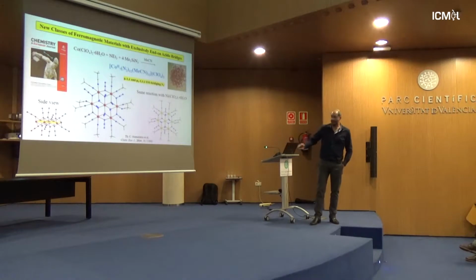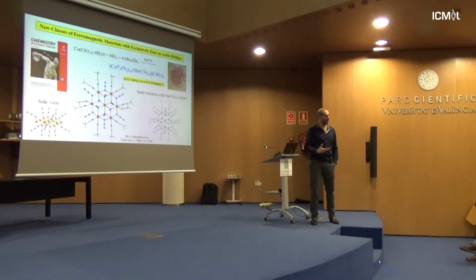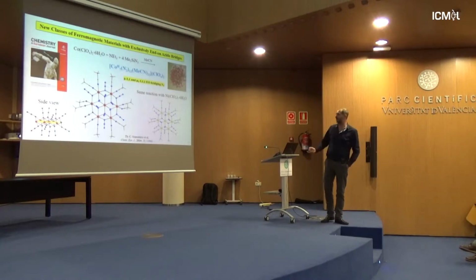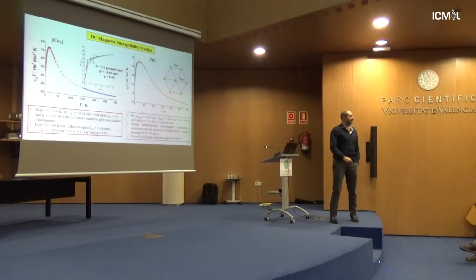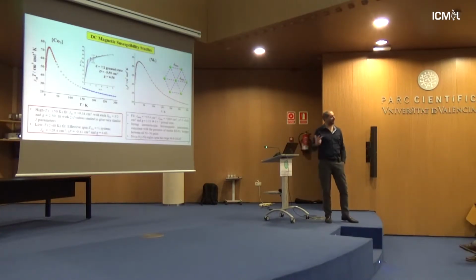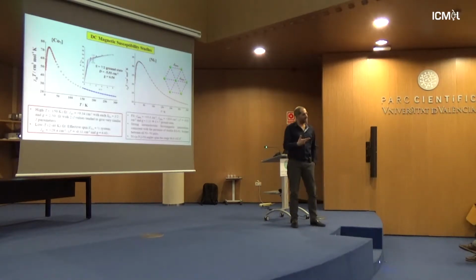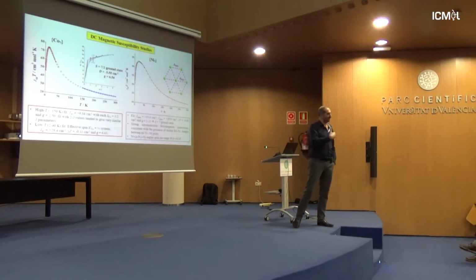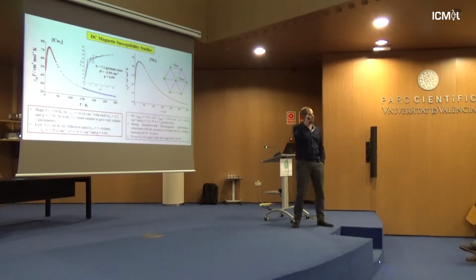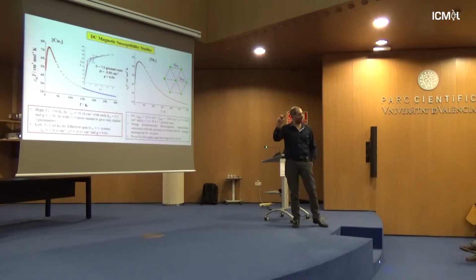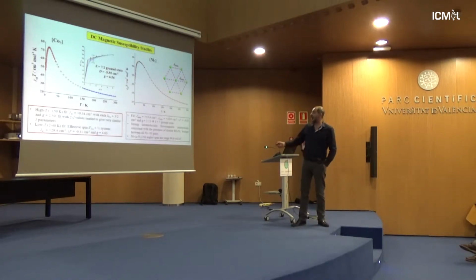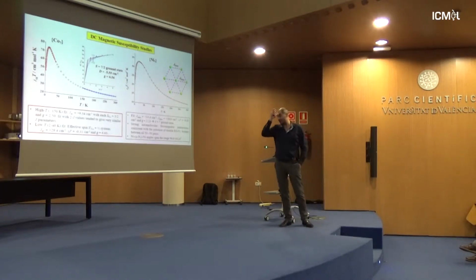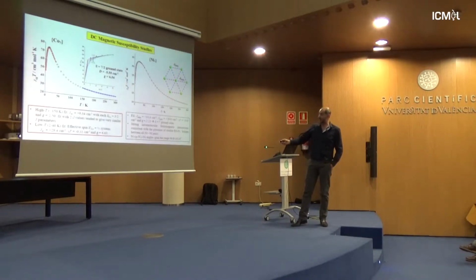So for us it was important that we had those two compounds, and if our theory was right, which is not something surprising, we will have what we see here, predominant ferromagnetic exchange interactions in both cases, and the maximum spin ground state for both families of complexes, for the cobalt-7 and nickel-7. So for us it started meaning that we can start building on something like a guaranteed route to high spin molecules with maximum spin ground states. So in the case of cobalt, we collaborate with Albert Escuer in Barcelona, and we tried also to fit the data.